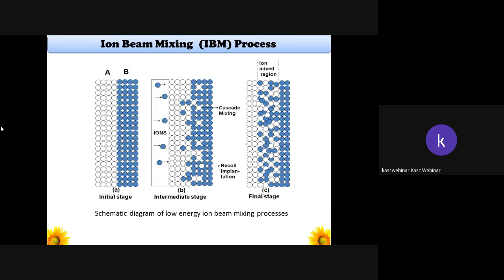Then the ion beam mixing process. Actually, figure A indicates the bilayer sample, where B may be taken as a support medium or a substrate, and A may be a deposited layer. If the sample is subjected to ion beam irradiation, it is represented in the intermediate state. The energy of the incoming ions may be transferred to the lattice points, and the layers get mixed, or a little bit mixed layers will result. But at the end of irradiation, we may expect that a certain amount of the layer remains unmixed in part A and part B, and the ion mixed region or vortex region is also possible after the end of irradiation. Especially this is the case for low energy ion beam mixing.